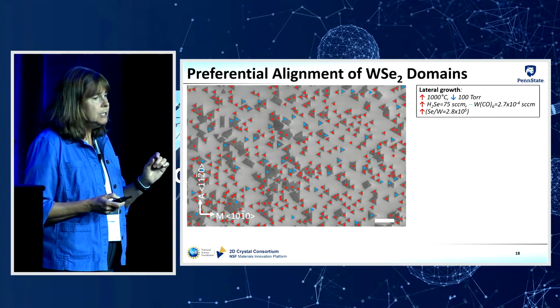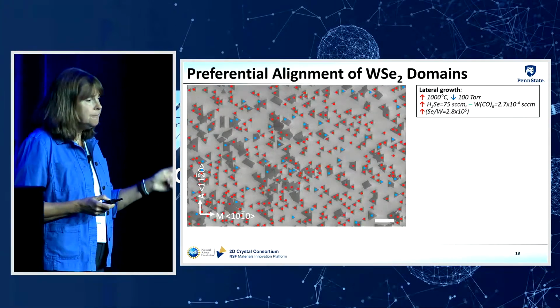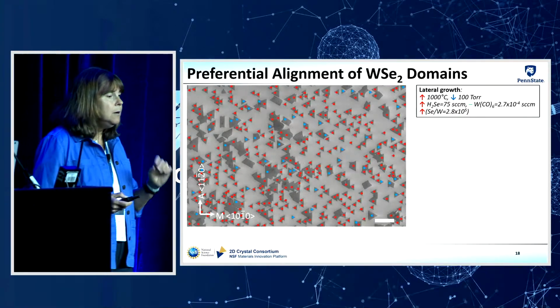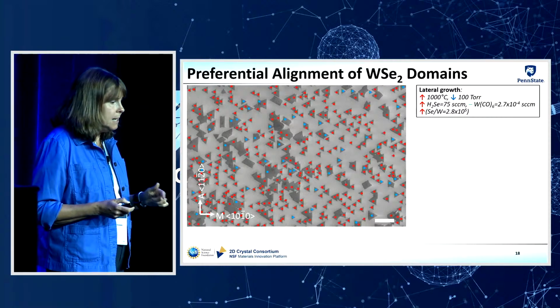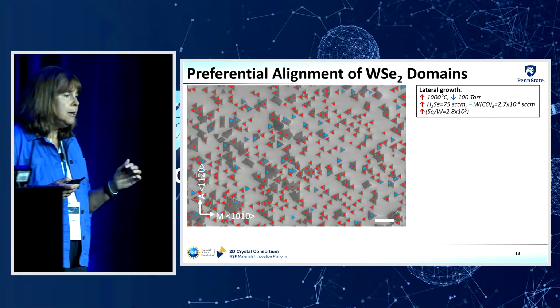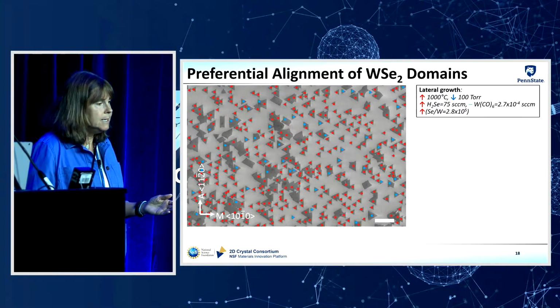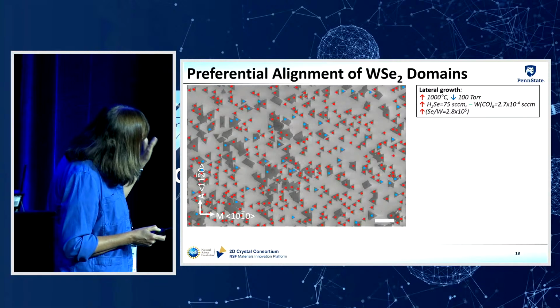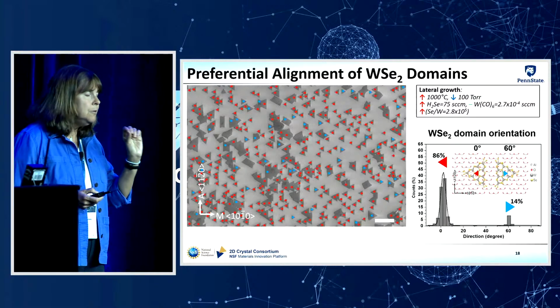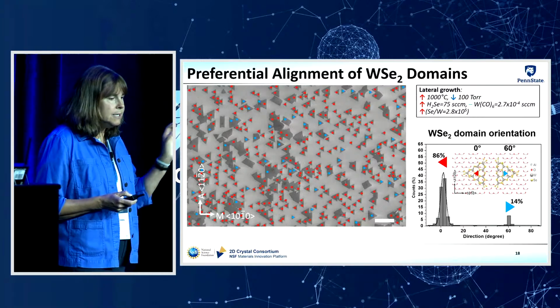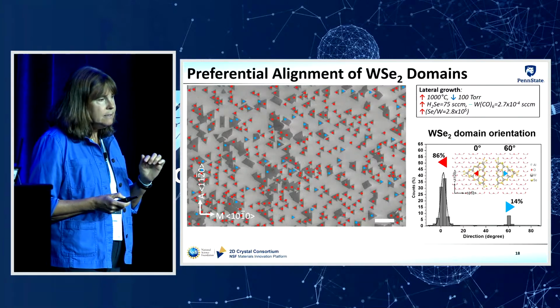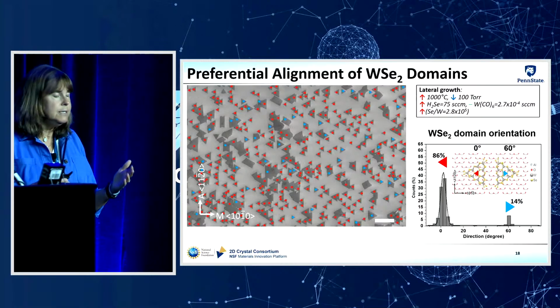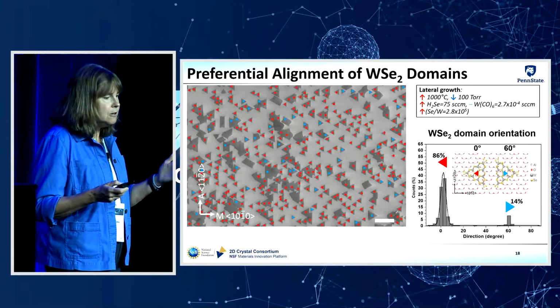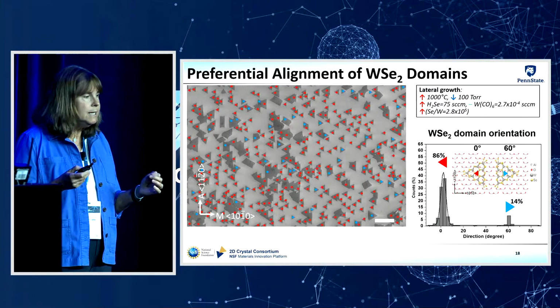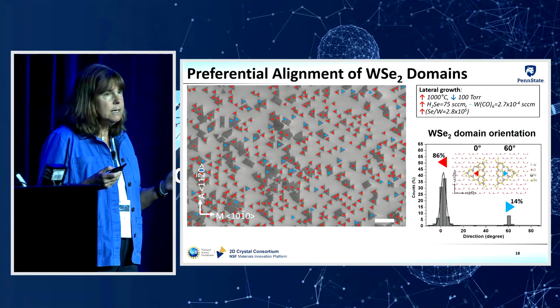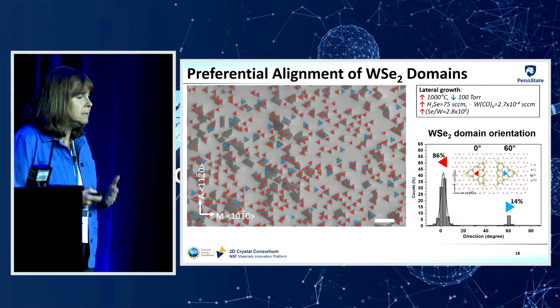But we modified the growth conditions a little bit. We increased the growth temperature from 800 up to 1,000 degrees C, and we increased the flow rate of our hydrogen selenide even further. What we found is that we got a preferential orientation for our tungsten diselenide domains. I've color-coded them using red and blue in this case. The red domains have the 0-degree orientation, and the blue domains have the 60-degree orientation. You can see that there are many more red domains than there are blue domains. So we have a clearly preferred alignment for our tungsten diselenide domains, which is what we want in order to minimize inversion domains in the film.